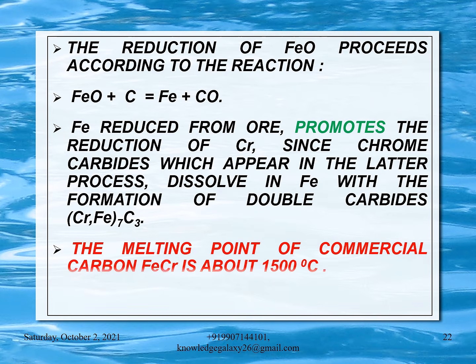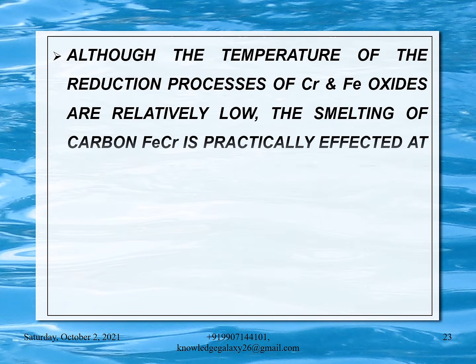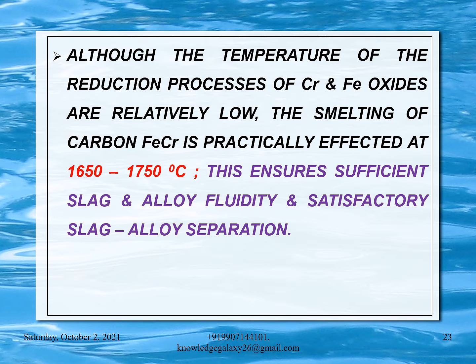The melting point of commercial carbon ferrochrome is about 1500 degrees Celsius. Although the temperature of the reduction processes of chromium and iron oxides is relatively low, the smelting of carbon ferrochrome is practically effected at 1650 to 1750 degrees Celsius because this ensures sufficient slag and alloy fluidity and satisfactory slag-alloy separation.